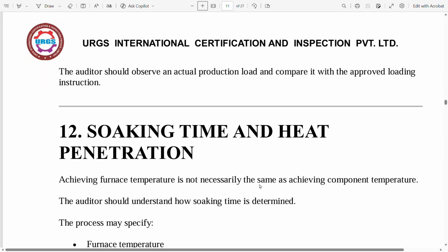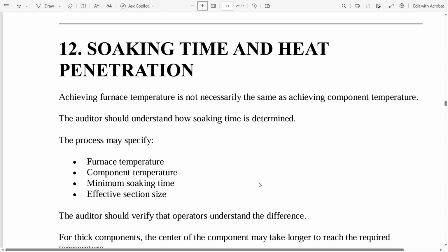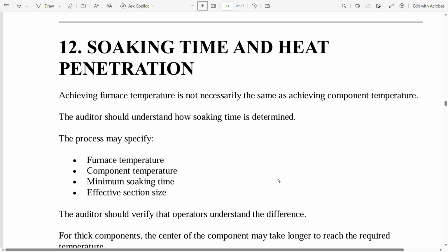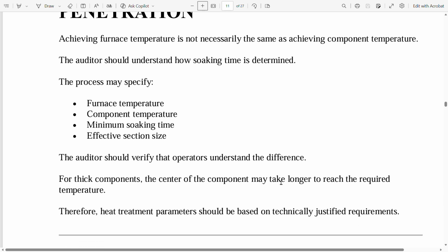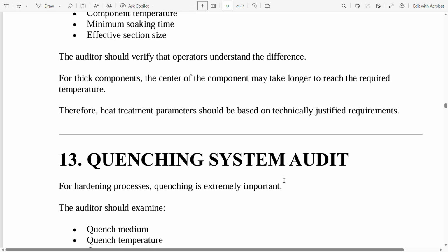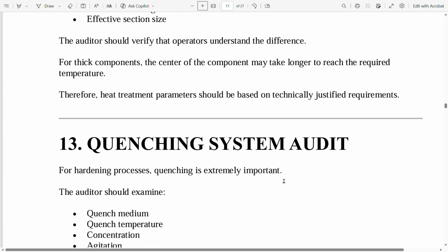Now next is soaking time and heat penetration. Achieving furnace temperature is not necessarily the same as achieving component temperature. The auditor should understand how soaking time is determined. The process may specify furnace temperature, component temperature, minimum soaking time, effective section size. The auditor should verify that operators understand the difference. For thick components, the center of the component may take longer to reach the required temperature. Therefore, heat treatment parameters should be based on technically justified requirements.